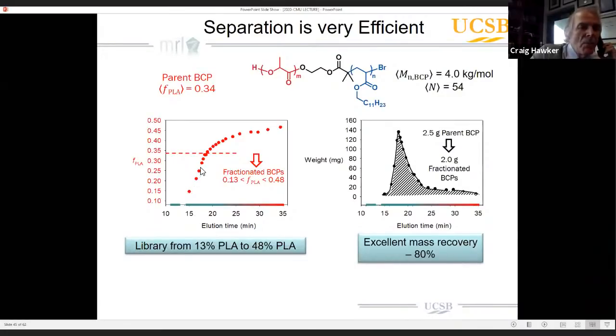Then as we collect more and more fractions, we increase the amount of lactide until our final fractions are 48% polylactide. Now, one of the important things that we've always focused on in this work is: is it synthetically useful? Do I get much material out? And you can see from this plot that you do get a very good mass recovery.